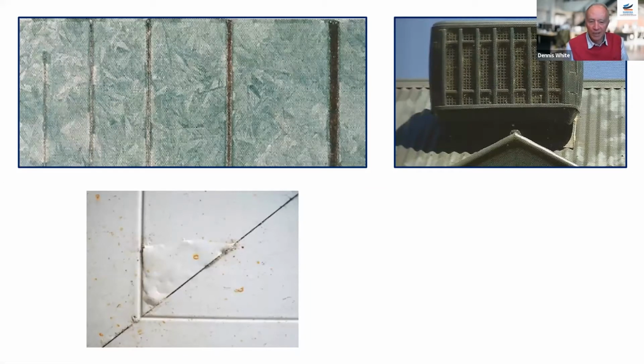One of the unique things of the metallic surfaces is the cathodic protection, and I guess the best way of describing cathodic protection is like your skin heals when you cut it or scratch it. But depending on how big the wound is, you may need to stitch it. And when you've got a metallic surface, you've got this constant flow of moisture across that surface, which creates this flow of ions, and which is a self-healing process. But once you get beyond a certain width of gouge, scratch, or where the surface has been damaged, the coating can no longer cope, and you will start to get rust spots on the surface of your cladding.